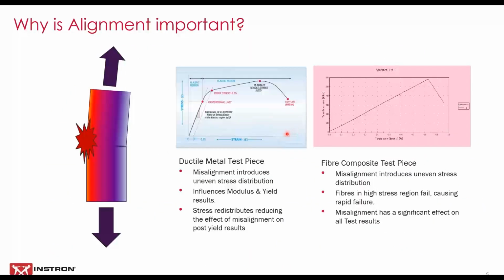Well, obviously, if we're not achieving a uniform strain and uniform stress state in the specimen, we're going to have higher stress areas and lower stress areas. We're going to get yielding in part of the specimen that's under the higher stress. In a metals test, we get an uneven stress distribution from misalignment. It's going to influence the modulus and the yield results. If we had an extensometer on this side of the specimen, it's going to read less strain than on this side, and on the other hand, the axial stress is going to be more or less the average stress. So it will influence the modulus results. It's going to give us an incorrect yield result as well.